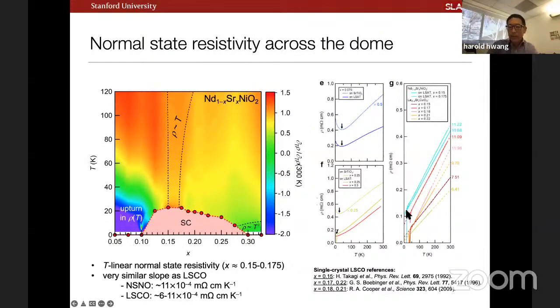And what's quite remarkable in my mind is that that slope in real numbers is very close to that of the 214 cuprates. For example, this is like 17.5% nominally. If I compare that to 17% doping in 214 cuprates, it's virtually identical. So these are the slope values, if you're interested, in milliohm centimeters per Kelvin of the nickelates, as well as some cuprates in this linear regime.